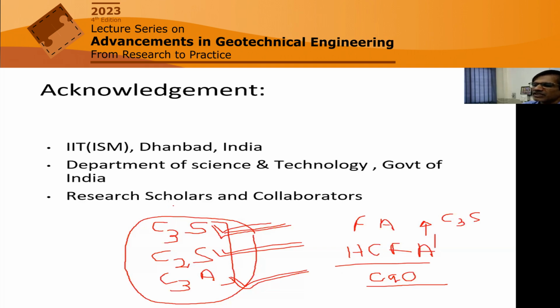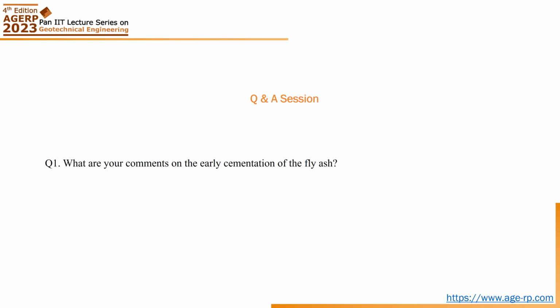Then again coming to the chemical composition: in the cement, the lime content, the CaO content, is almost 60%. Whereas in fly ash, even the high calcium fly ash, the maximum is 20%. So the percentage of cementitious material in fly ash is much, much less compared to that of cement. Depending upon the type of minerals present, the strength of the high calcium fly ash will be different, and in the long term it may not be there. And the other one, sometimes we get the leaching question. In that case, if you put it again in water, part of it will get dissolved, and the pore space will fill up with water, and then it may lose strength. So that's another aspect of this fly ash material.